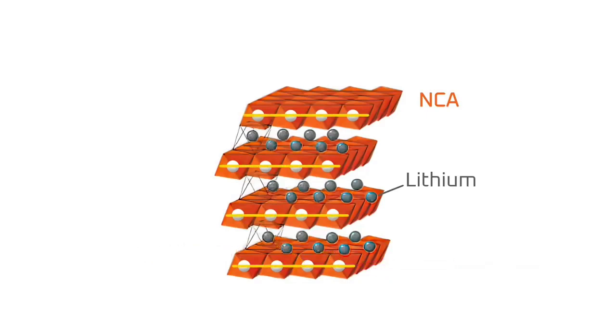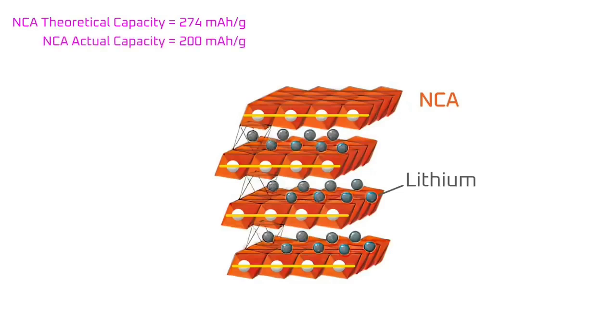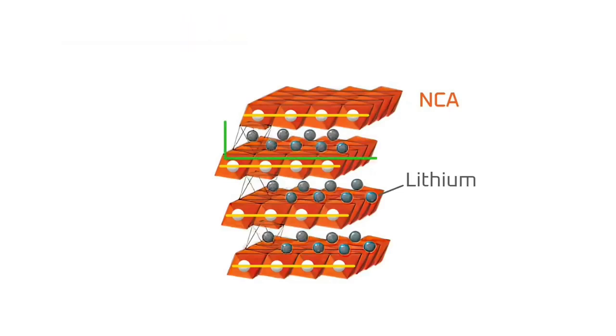Well, the crystal structure is weak. As lithium is removed from the lithium slab, the crystal structure becomes weaker and more reactive. Even though the NCA crystal structure can hold quite a bit of lithium at 274 milliamp-hours per gram, the amount of lithium that can be safely removed limits that capacity to around 200 milliamp-hours per gram. Some of the lithium ions must remain in the NCA crystal structure to serve as pillars to hold up the nickel oxide slabs, which would collapse without the lithium.